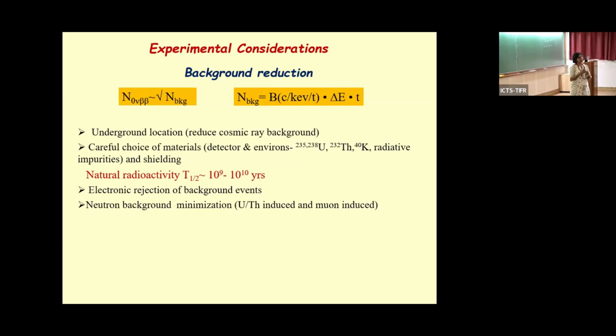And that is the reason I said that if you have a Q value above 2 MeV, it is preferred, because then the background due to the natural radioactivity can be reduced. Better than that, 3 MeV is even better. So you also have to make clever detector designs, with electronic rejection of background events. The other challenge is to minimize the neutron background, because neutrons are everywhere. In the last talk you heard about dark neutrons. I'm right now not worrying about dark neutron background. We are just looking at this neutron background right now.